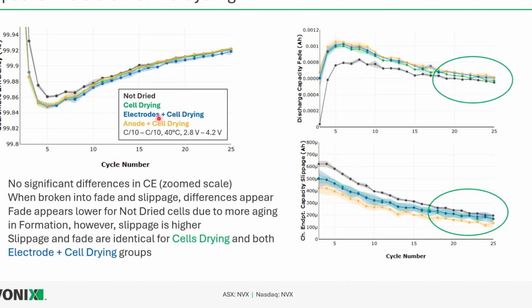And that's what we're considering here, this effect that's making basically the cells that were dried without drying the anodes and cathodes and the ones where all of the electrodes were dried together perform exactly the same. Because in both cases, the anodes and the cathodes exposed to ambient moisture are put in the oven and baked together and exposed to the moisture that's trapped in the anodes. So in this case, the anodes were baked, but they were put with fresh cathodes that hadn't been baked with anodes before.